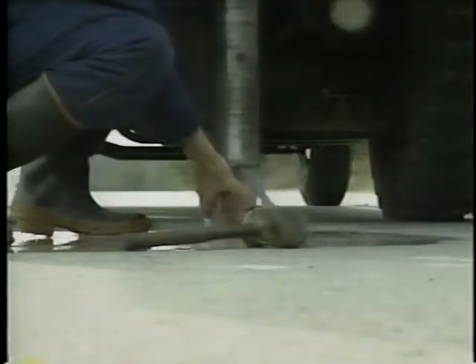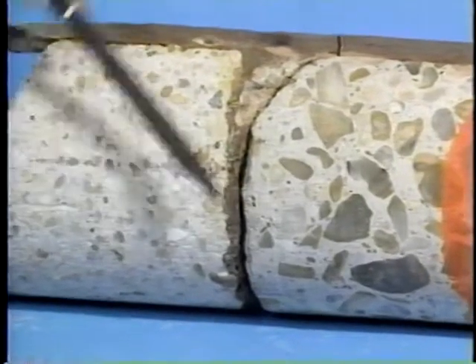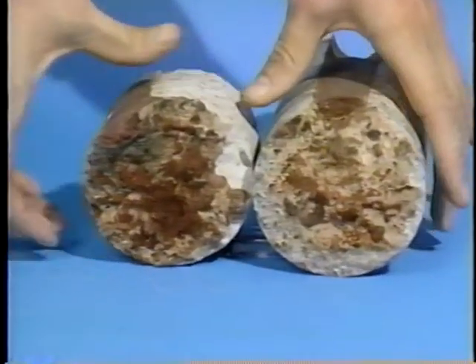When the epoxy is hardened, you take a four-inch core sample. The red epoxy will indicate if there is a problem and show its thickness. By pinpointing where under sealing is needed, this new procedure can save you time and money.